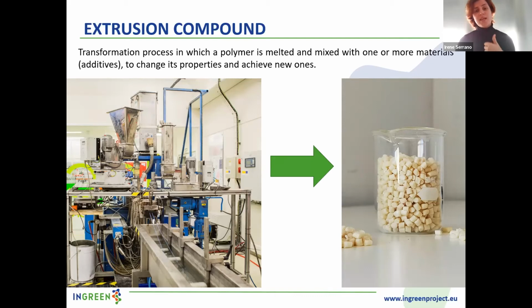The extracted PHA, a thermoplastic bio-based matrix, and the necessary additives are fed separately into a heated barrel that can have 1 or 2 screws continuously rotating inside. The barrel is also equipped with separate temperature controls that can be adjusted depending on the material that is being processed. The resulting high shear forces between the screw and the material, plus the effect of temperature, lead to the melting of the polymer and make possible the mechanical mixing of all the components.